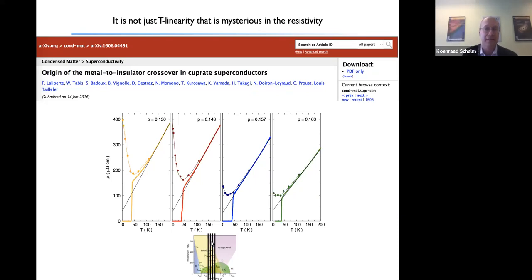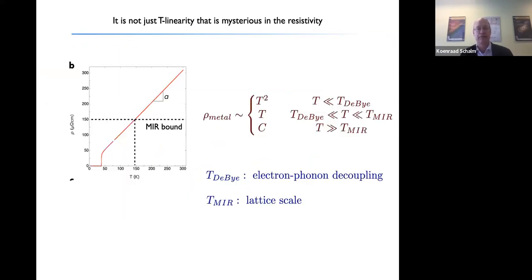And it's not just the linearity in T that's robust, let me emphasize, it's the fact that it doesn't change, even though you know that at various temperature regimes, the ordering behavior of the high Tc superconductors changes. So that is in itself a very big mystery. In ordinary metals, that's exactly what you see. The classic, simple theory of ordinary metals is that there are three regimes for how the resistivity behaves. I already told you that below the Debye temperature, below the phonon decoupling, you expect the resistivity to behave as T squared. Above the Debye temperature, there's a regime where the resistivity is linear in the temperature.